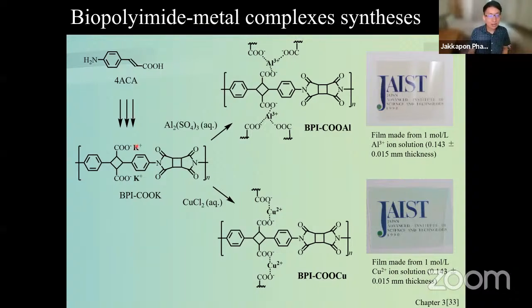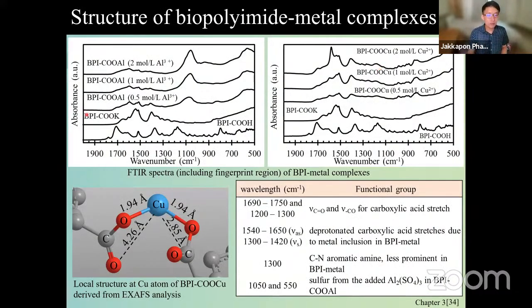But you see that I created the COO minus here and exchanged this with aluminum and copper, okay? And this becomes an organic-inorganic composite because aluminum and copper have some flame retardancy property. So I just chose these metals. Okay, and here are the films. They are quite transparent, as you can see. This is the green one, the copper one, and this is the aluminum, which is quite transparent. Now, here is the absorbance against the wavelength. This is just a study to see what changes when we have incorporated the metals in there, okay?